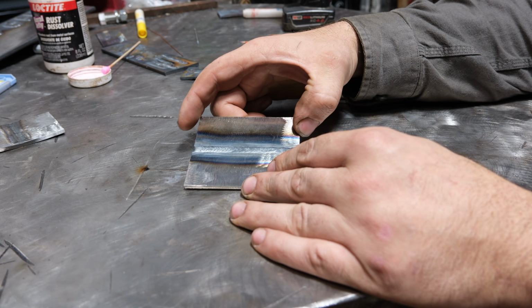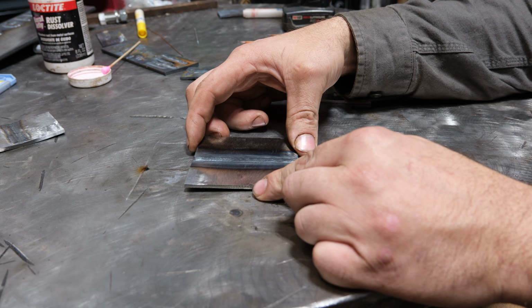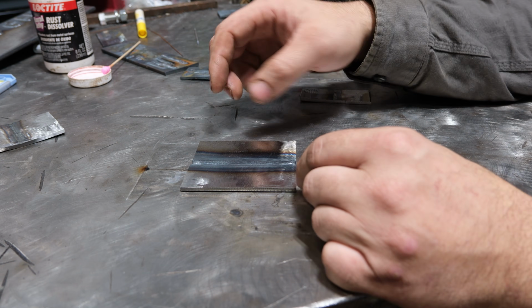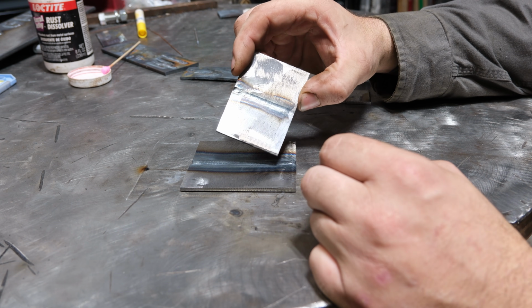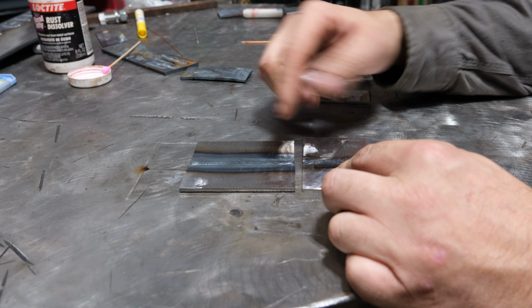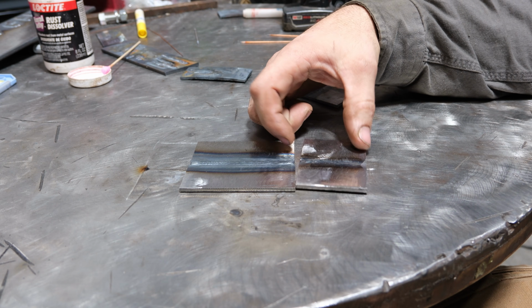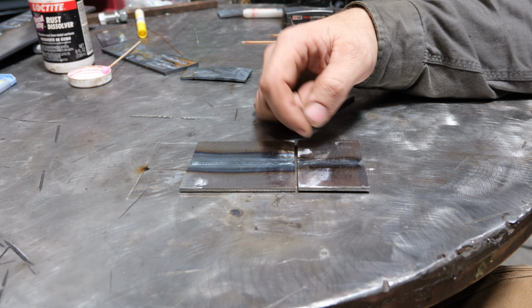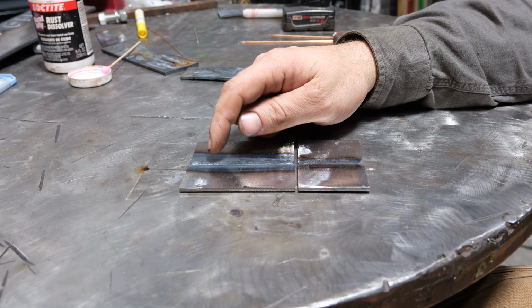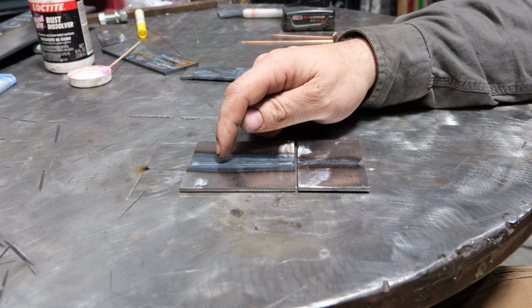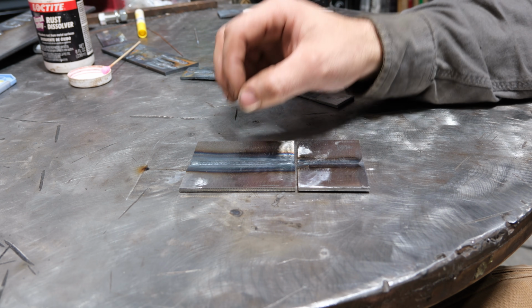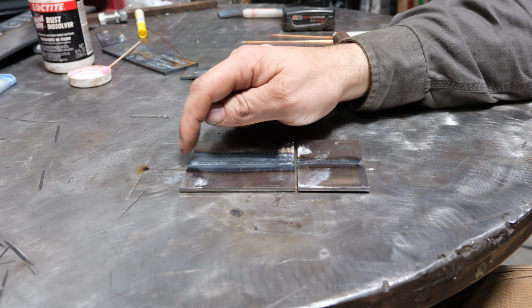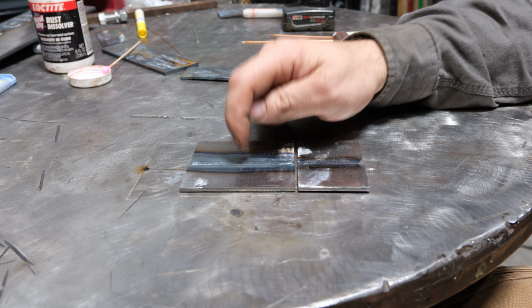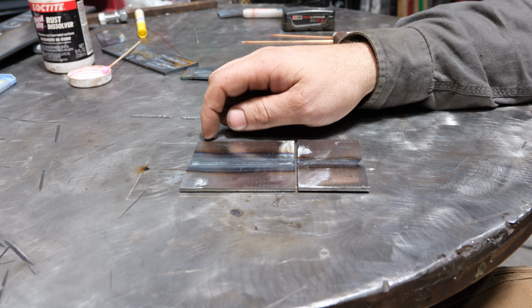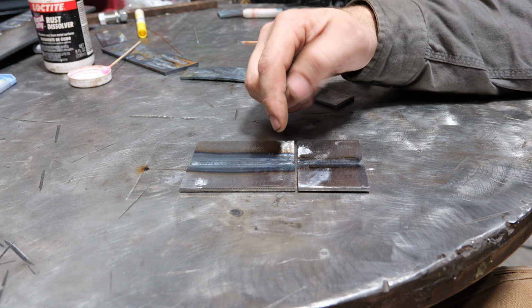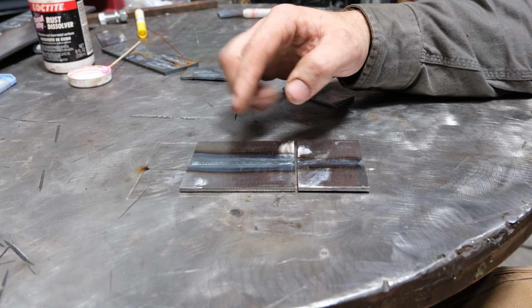So here we have the weld I just ran, and I ran it with filler, same 120 amps. Now there's a couple key differences that I want you to pay attention to. Here is our weld that was just a fusion weld, and if you notice, the heat affected zone lines are both wider and more prominent. The bead itself is also wider. That is because while I was adding filler, I had to wait longer at 120 amps to make sure that everything was hot enough that the filler melted, that the weld wetted out, etc. By doing that, my travel speed slowed down, therefore my heat input per second increased, therefore we have much more heat input and wider heat affected zone lines.